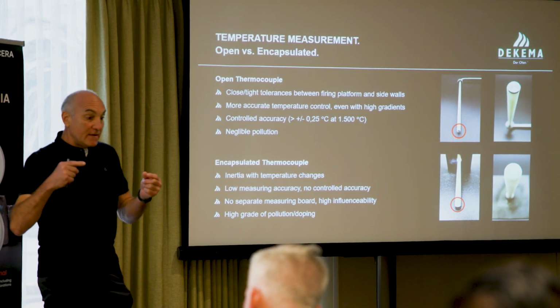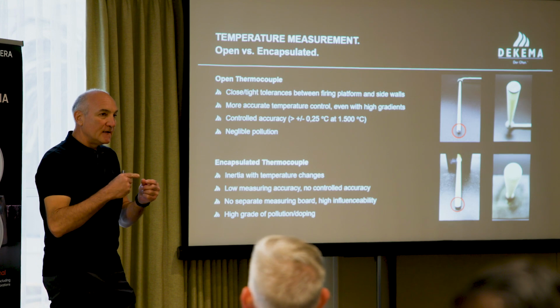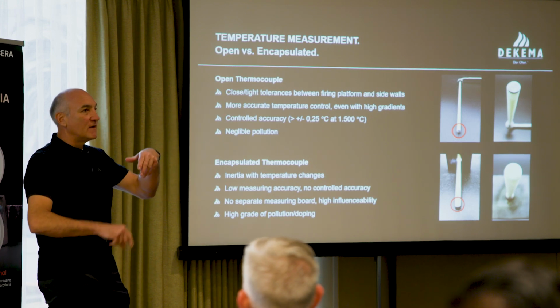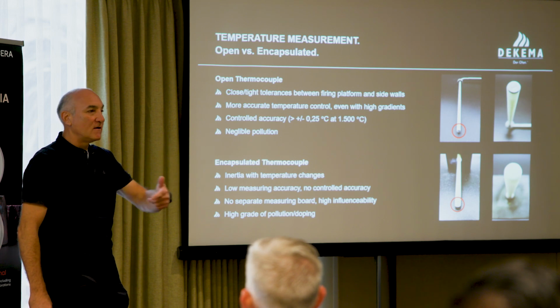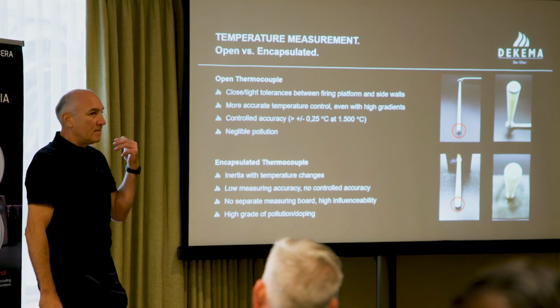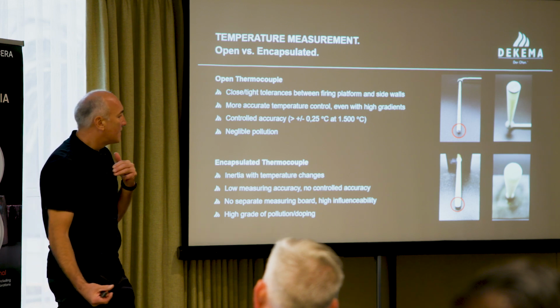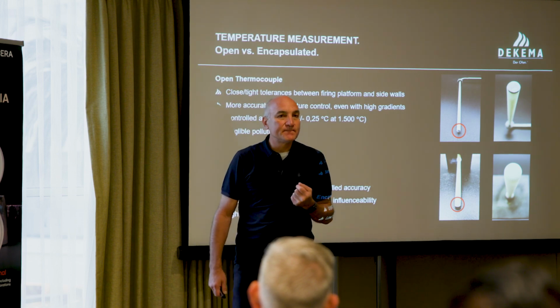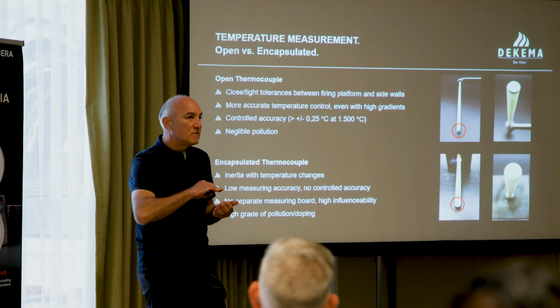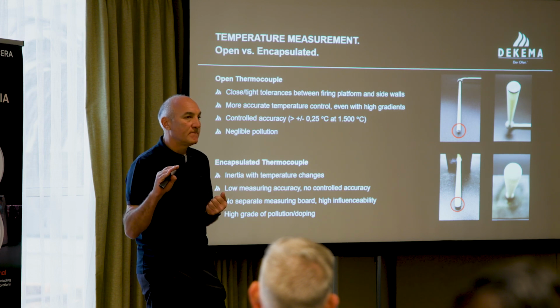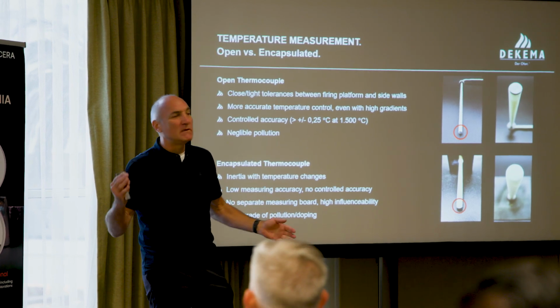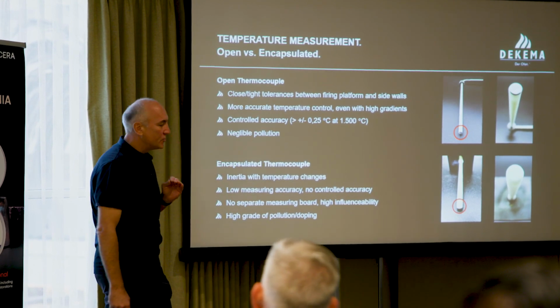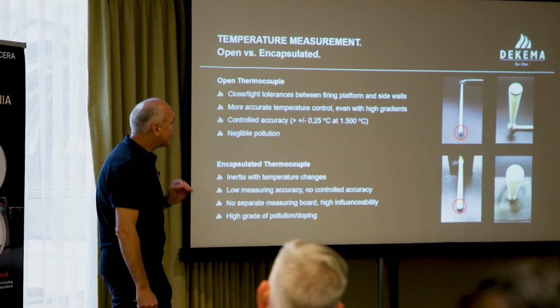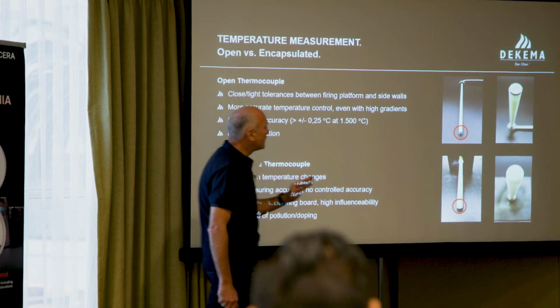And not only that, it's not only the temperature which is going through, it's even the pollution inside. You have lots of pollution. You have pollution through the zirconia, through the coloration, through acids, not with us, but even through heating elements. And this is accumulating on this alumina part, leading to a permanent temperature change. And this is what we want to diminish, what we want to hinder, negligible pollution. How do we do that? As I said, it's patented. First of all, like all DEKEMA furnaces, the thermocouple sees the real radiation.